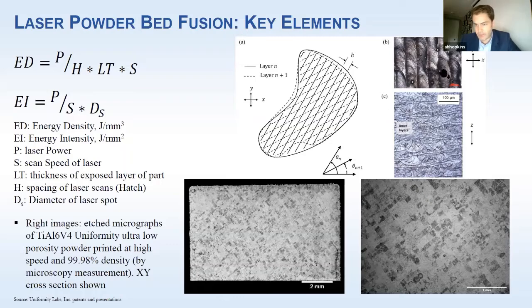There you can see tracks from above. They're very repeatable over most of the build, but if you're going to put a part in an aircraft engine or in space, very repeatable over most of the build doesn't cut it. If you have a 300 micron pore or a 200 micron pore, which is the width of the melt pool, you're out of luck. That part is potentially going to fail, and it's not useful in the commercial space. So you really need to be precise over a broad area of the part.